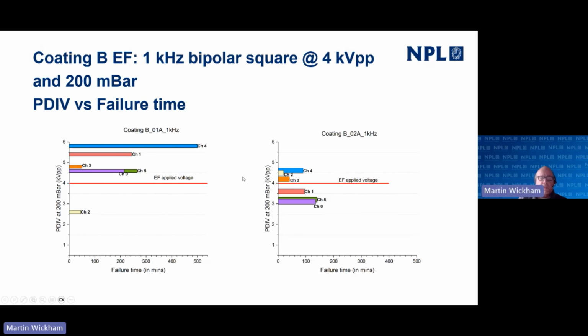This shows a slightly different plot with the same information on. This is our first set of samples, this is our second set of samples, and as I indicated to you before, in our first set of samples, the inception voltage was pretty much all above the applied electrical fatigue voltage, yet they still failed. So this one failed at 500, this one at 250, this one at 275, etc.